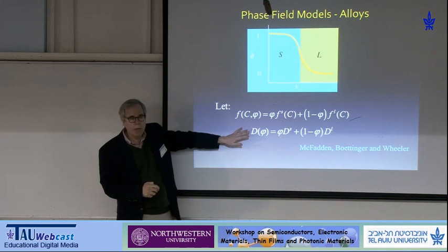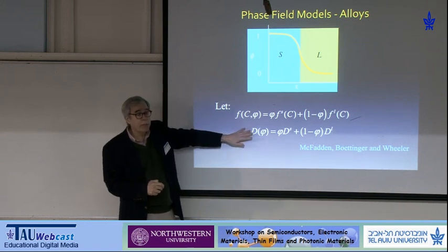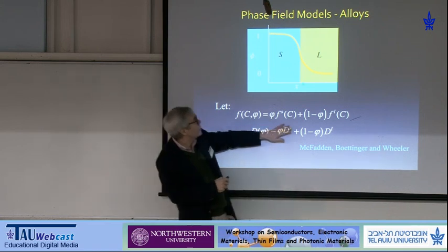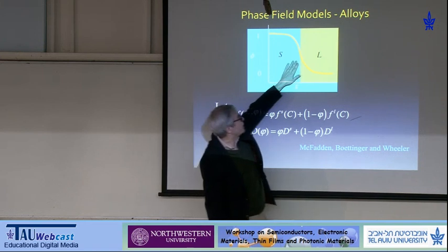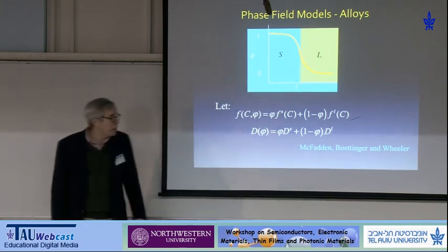But the takeaway message that I want you to be aware of is that whenever you see a phase field equation, a model, so this could be ferroelectric thin films, this could be magnetic materials, if you have structures that vary across the interface and you're interpolating across the interface, you will get physics at the interfaces that depend upon these interpolation functions that sometimes can be a problem.